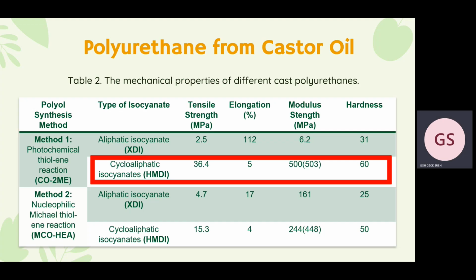The mechanical properties of the four different PU polymers that derive from the castor oil polyols are summarized in Table 2. Based on the table, it has been noted that the PU polymers produced by curing the polyols produced via method 1 with the HMDI isocyanates have the best mechanical properties. This PU polymer has a tensile strength of 36.4 megapascal, elongation of less than 10%, modulus that ranges between 244 to 500 megapascal, as well as the highest hardness value.